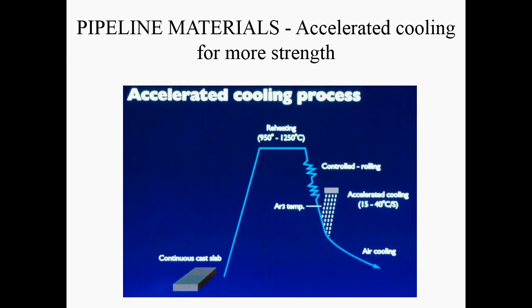So what's the accelerated cooling process like? Well, it's quite straightforward. You have your continuous cast slab, you reheat, hot rolling, controlled rolling, water spray, accelerated cooling, and then once you get down to around 300-400 degrees C, then you allow the air cooling. Actually, the processes are quite straightforward, but controlling the processes to give you the microstructure that you want, that's less straightforward. And that's the skill of the steelworks.